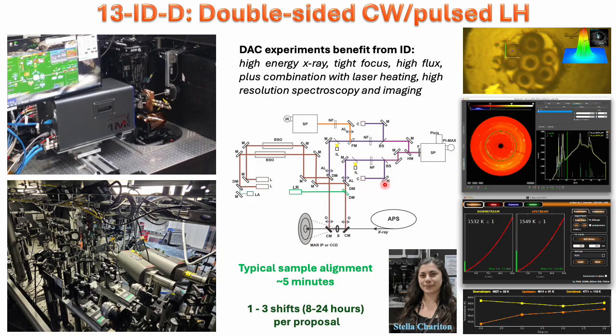At this beamline station, we have a unique laser heating system where we are using a flat top focal spot, and that allows us to collect X-ray diffraction data from the uniformly heated sample within the X-ray beam size. As you can see, the X-ray is inside the flat top heating spot. It means that the lateral temperature distribution is minimal. And in automatic mode, you can press a button and it will turn on the laser, collect an X-ray diffraction pattern, measure the temperature, and show it to you on the screen, and you can focus only on the scientific point of your research.